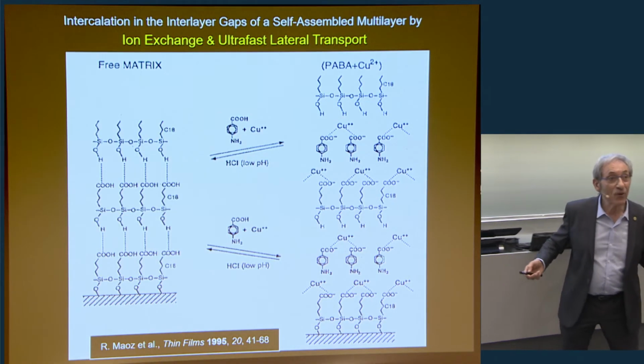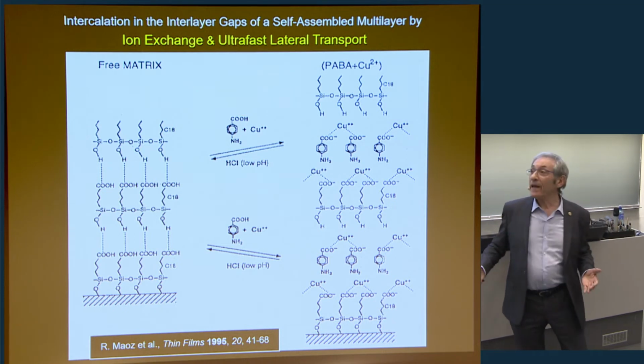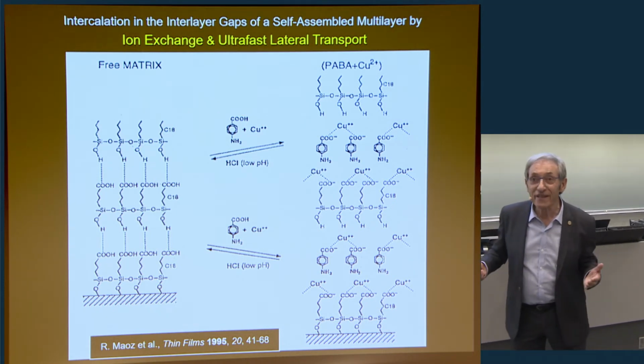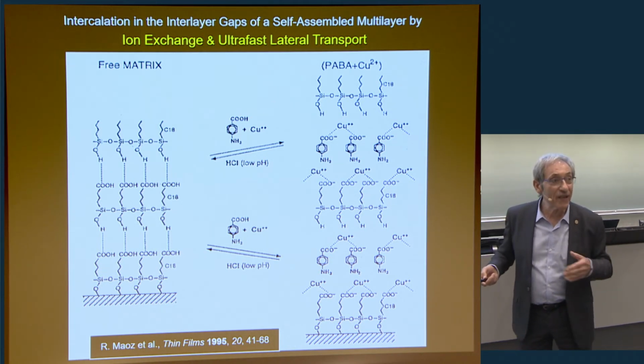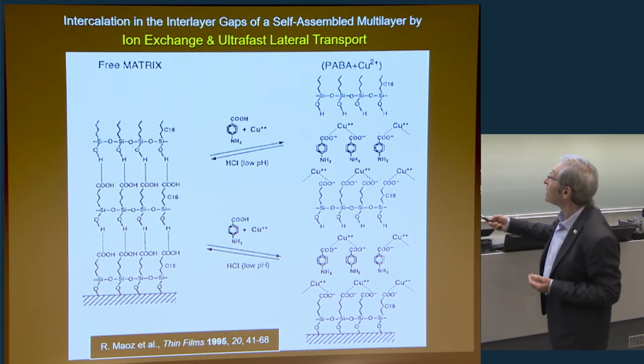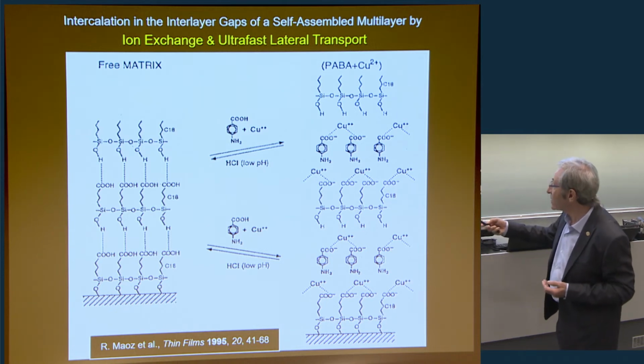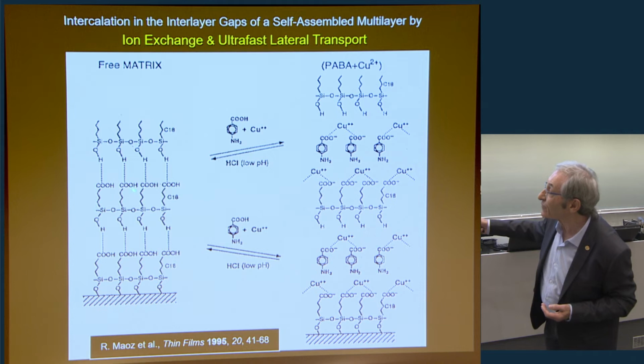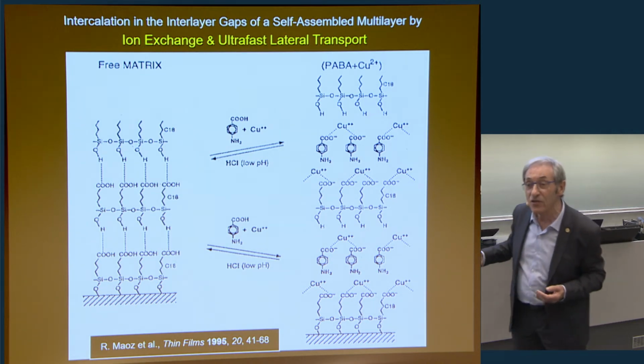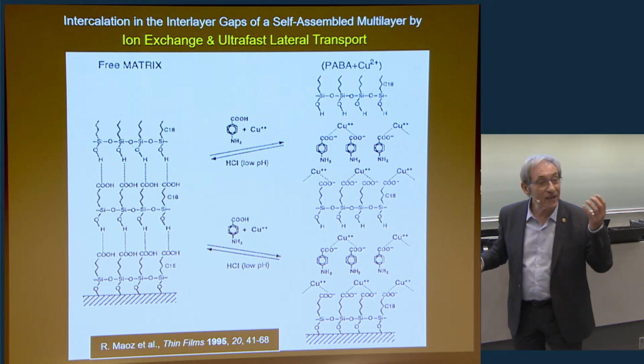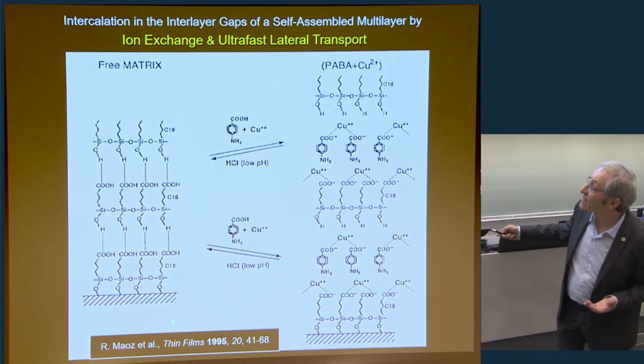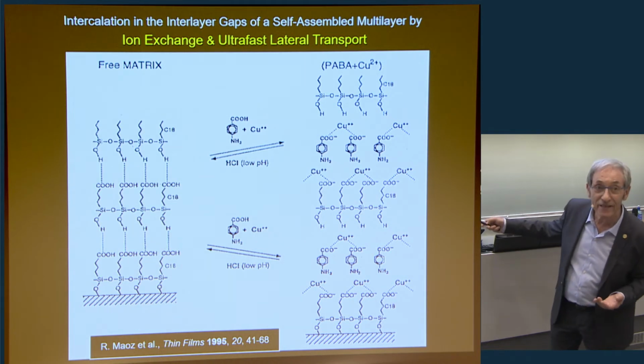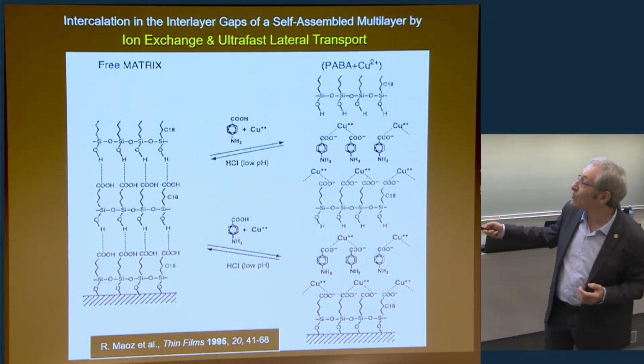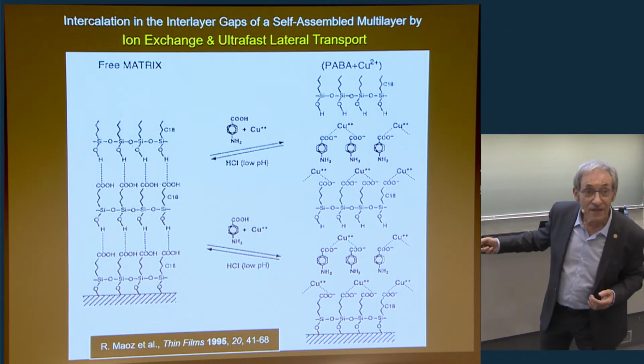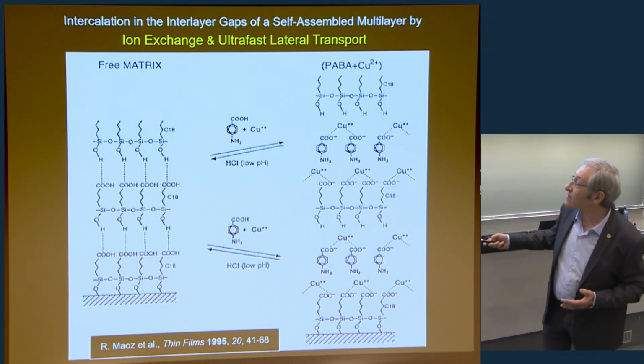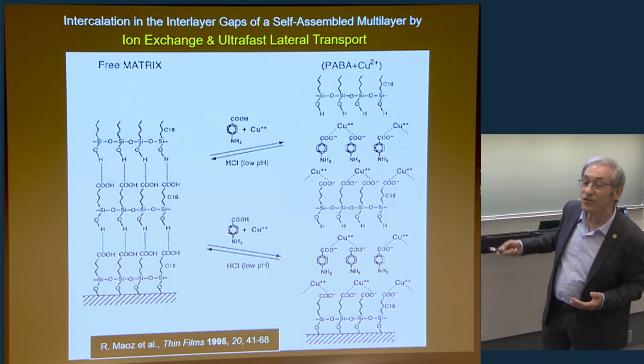Now, with this approach, we could really build. And another discovery was that we don't need covalent bonds from layer to layer. It is possible to create multilayers in which the lateral bonding is sufficient and the bonding between the layers is not covalent, it is hydrogen bonding. And once we have such a, what we call a free multilayer matrix, in one step, it turned out to be possible to intercalate ions and other molecules. And this is something extraordinary because this structure is non-centrosymmetric.